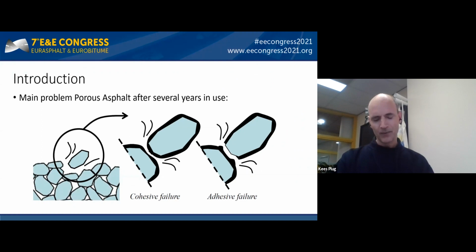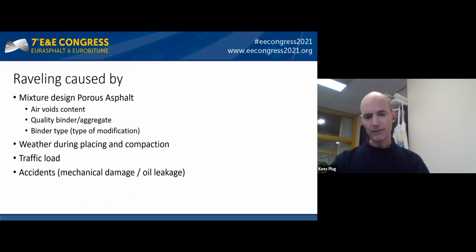The main problem of porous asphalt is raveling due to loss of stones, as can be seen in the picture. This can be due to cohesive failure, which is failure in the asphalt mastic, or it can be due to adhesive failure, which is a failure on the surface of the stones. The problem of raveling can be induced by several factors. A poor mixture design with a wrong combination of materials, and weather during placing, cold and heavy rain during placing, will not help for good quality.